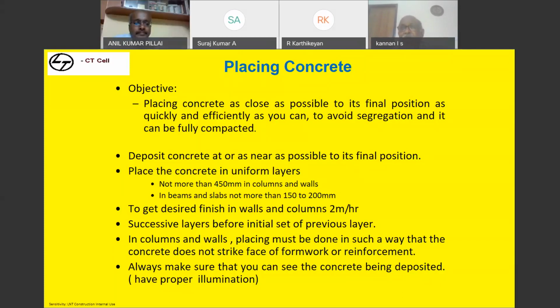We can stitch. Okay. So the requirement is that successive layers need to be placed before the initial setting time of concrete. It is not that after 4 hours the concrete has hardened and it has become a construction joint. No, still it is in the green state if you are able to vibrate it.